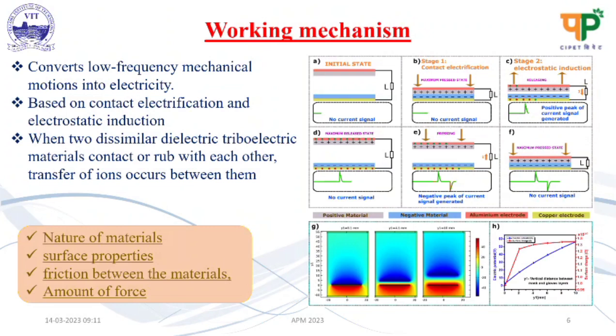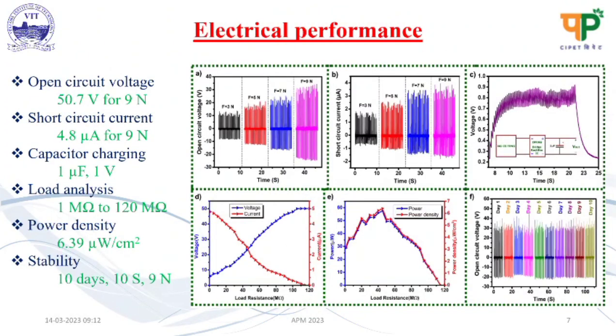Simulation analysis of MGCS TENG using COMSOL Multiphysics software was performed to visualize the potential distributions and the surface charge on the materials. The electrical performance of the device was tested for different compressive forces. It could generate a maximum peak to peak open circuit voltage of 50.7 volt and a short circuit current of 4.8 microampere corresponding to a maximum applied force of 9 Newton. And it was observed that both open circuit voltage and short circuit current increased with the applied force.